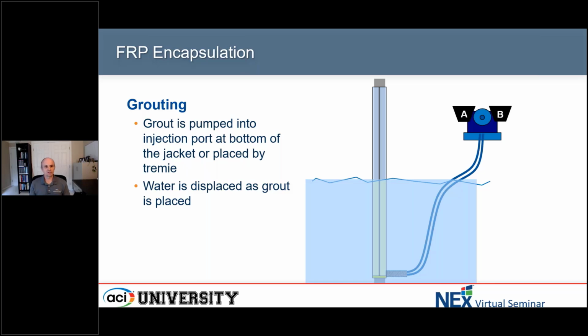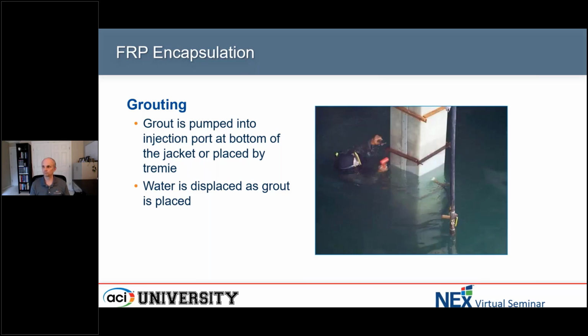Just to note that I'm showing this grout being pumped. Pumping is not the only way to place the grout. I'll talk about some of the different placement methods, but generally speaking, you're trying to get the grout placed from the bottom, working your way up to the top of the encapsulation. So we keep pumping grout until that entire FRP jacket is filled with grout. That annular space is completely filled, and we have a good quality bonded encapsulation of that existing structure.